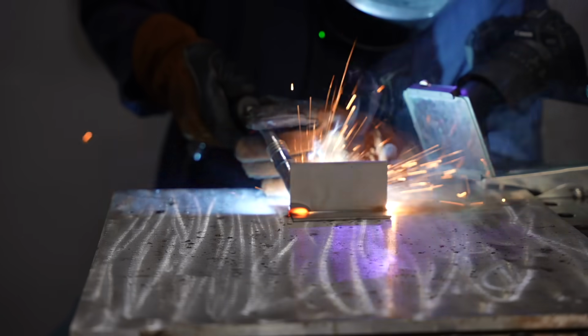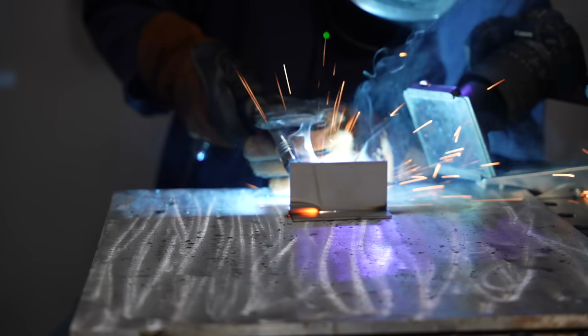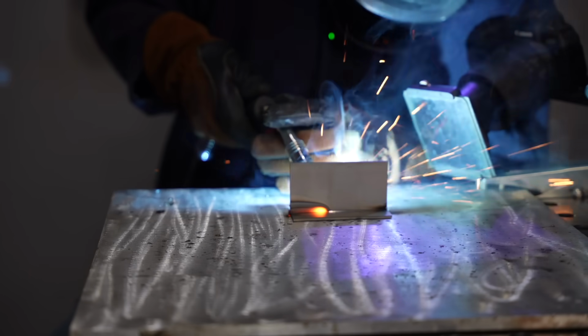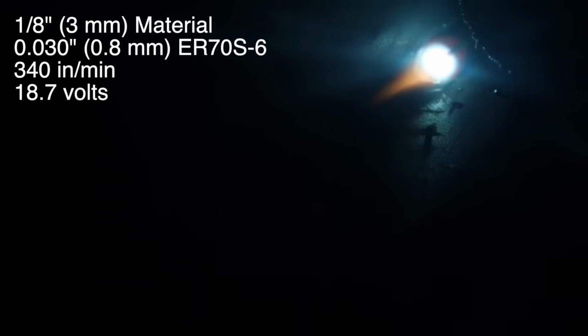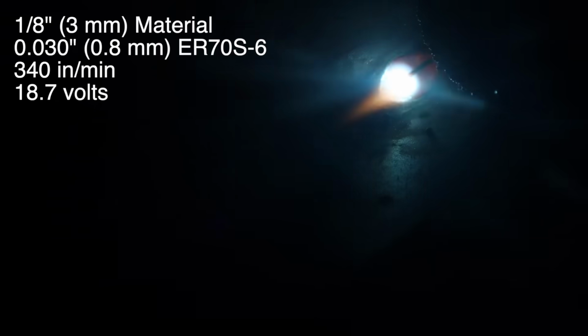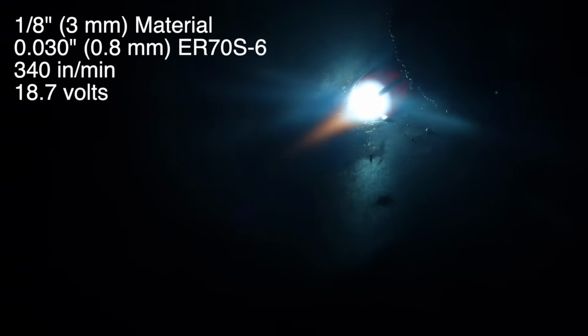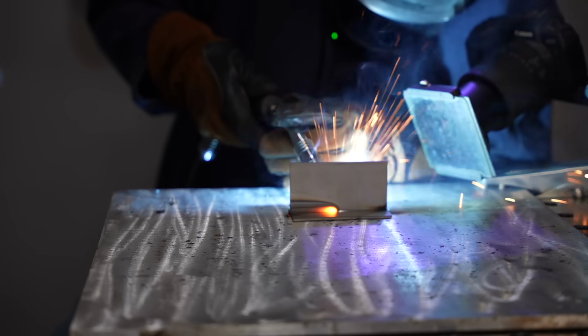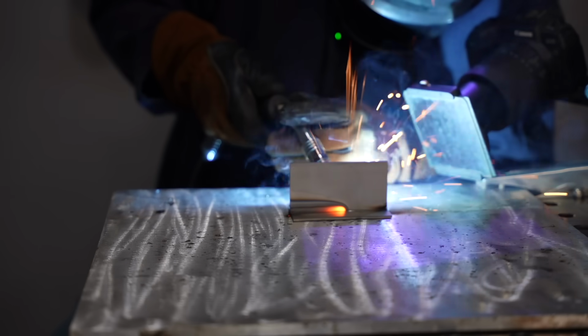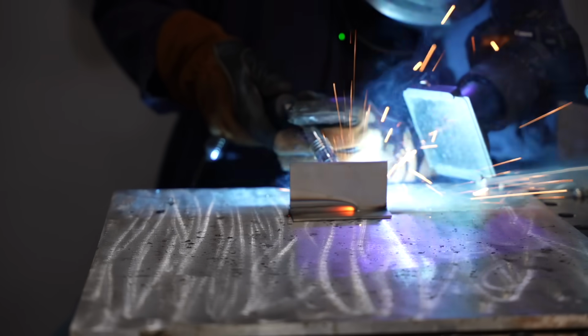Now I've moved to some 1/8 inch thick plate, and in doing that, I turned up my wire feed speed as well as the voltage to a more appropriate level so I get some more amps. And because I did that with the same size wire, each time it short circuits out against the base metal, you're going to have a little bit more of a violent arc, and so you might get a little bit more spatter.